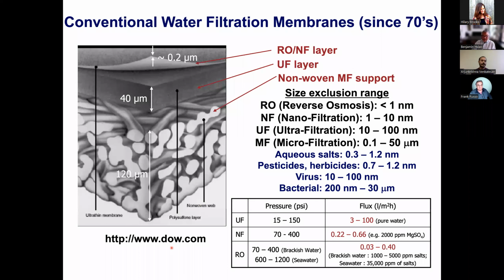It turned out this membrane technology had not changed since the 1970s or so. So typical membrane technology is you have this non-woven backbone, and you have this porous membrane, which is about 40 microns. You add this part, this is called the UF layer, and the pore size is about 10 to 100 nanometers. And once you add this, probably 20% of the materials compared to the rest, your value increased by about 1 order of magnitude. Then all of a sudden, materials become much more expensive.